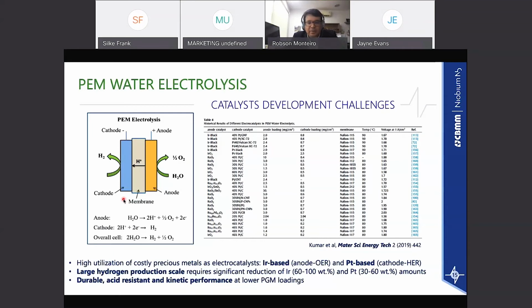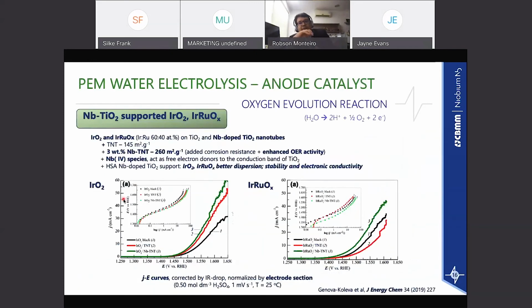Not only reducing the amount, but making them durable is also a great challenge, because the acidity of the membrane also helps decrease the performance of the materials, and of course the kinetic performance. This material really needs to act as a good catalyst at the end of the day. So what people are doing with niobium, when you think of the oxygen evolution reaction, which is the anode side of the PEM electrolyzer: one of the strategies is to better utilize iridium, which is the catalyst of choice of this technology. There are quite a few strategies for better utilization of iridium. One is to support the materials and make them more dispersed for better utilization, make them more stable, and also improve their electronic conductivity. In the end, we can increase the overall performance of the catalyst for the oxygen reaction.